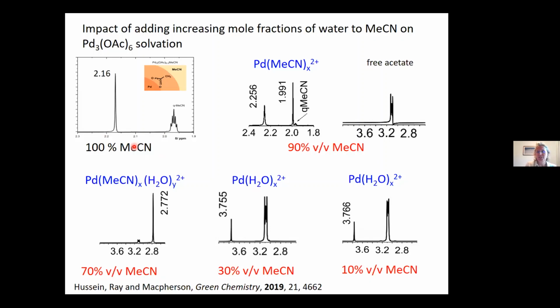However, as you start to put in small amounts of water, even when we consider just adding 10% of water by volume to an acetonitrile solution, that water loves the acetate. So what happens is the water acetate interaction is stronger. And what it does is it pulls it out of the inner solvation shell, and you start to free up that palladium for bonding to the solvent itself, which is acetonitrile. As you start to increase the water, you move from more of a pure acetonitrile bonding to a mixed acetonitrile water, to when you go to majority water, that palladium is well solvated with water molecules. At any point from 90% all the way through to 10% here, you can get electrodeposition because I've managed to get off those acetate ligands.